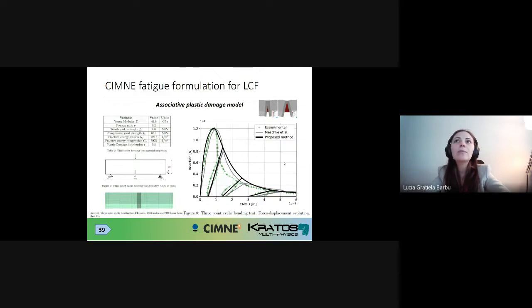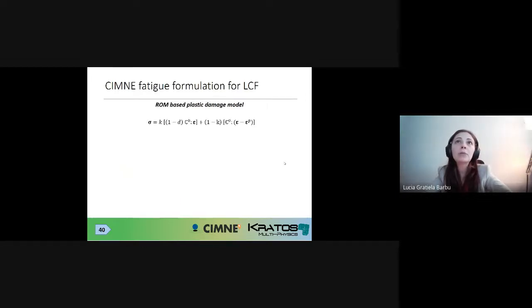We've applied this model, for instance, for a 3-point bending case, and we studied the crack mouth opening displacement with the reaction force, and you can see here the adjustment that we obtained. It was interesting, it was a good behavior. Then we go to the rule of mixture-based plastic damage model.